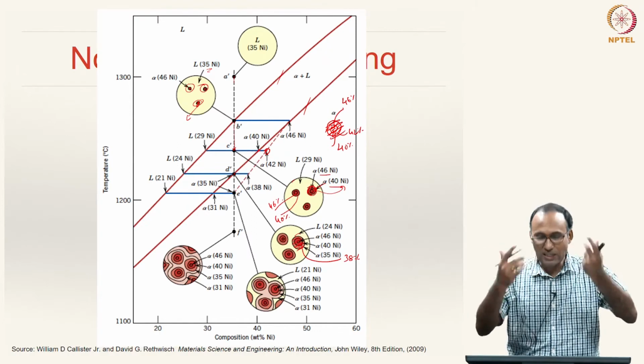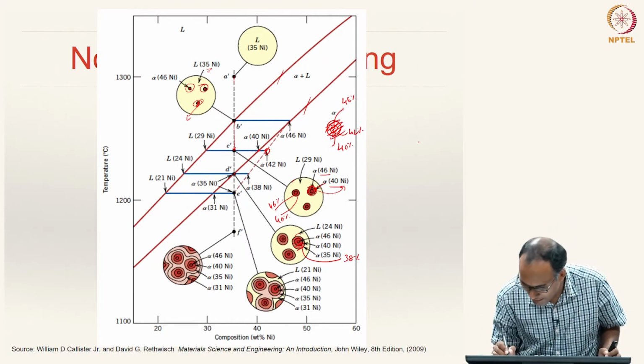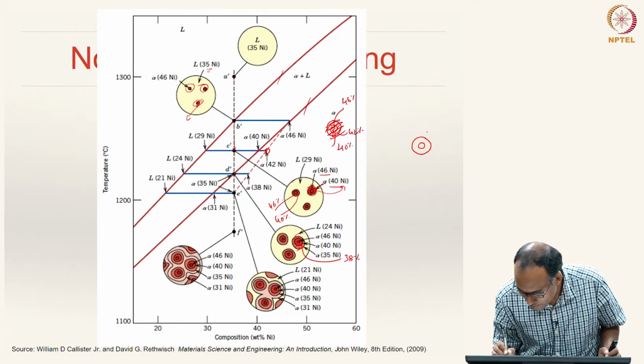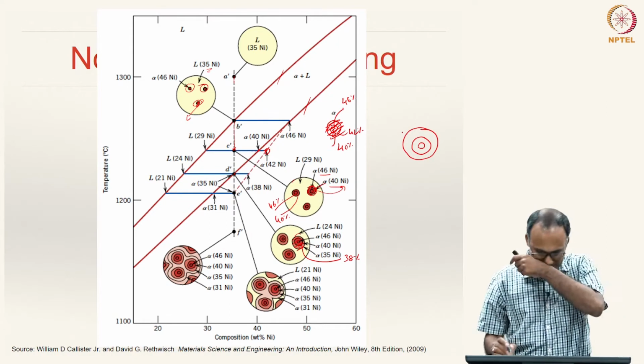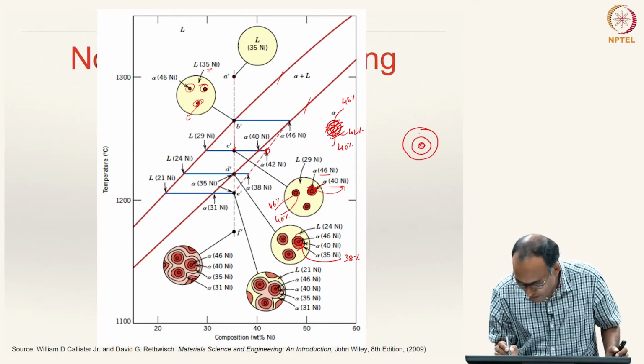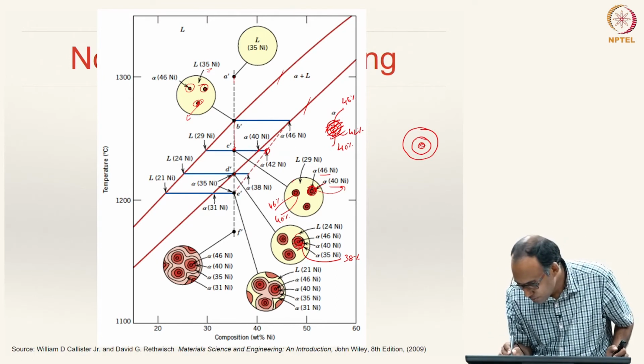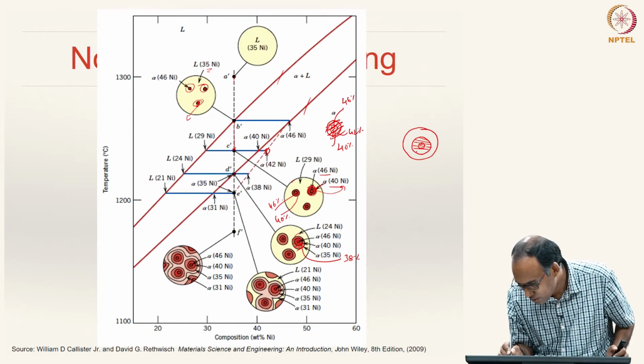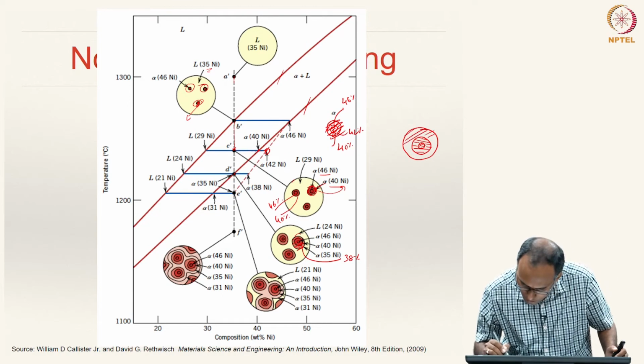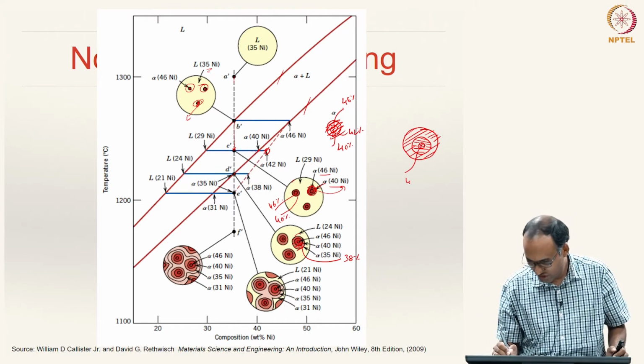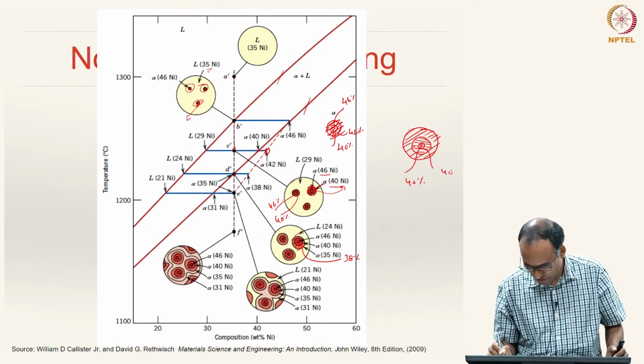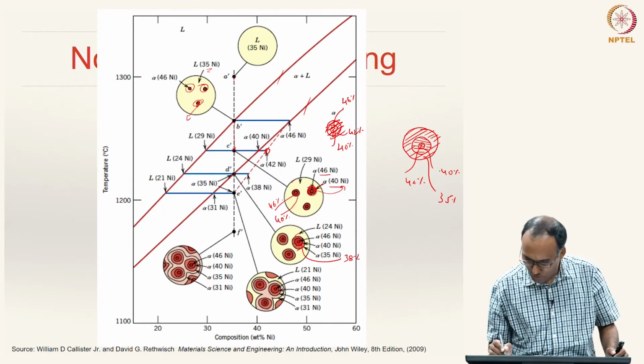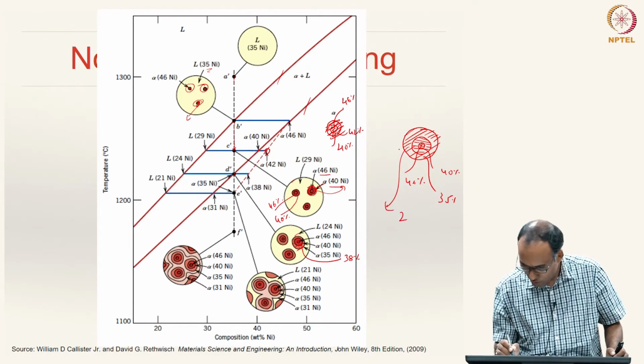That means, the solid grains that are forming, they are forming like this with different percentages of nickel. So, this is 46% nickel and this is 40% nickel and this is 35% nickel, and together if you take the average of all these things, then this entire thing will be 42% nickel.